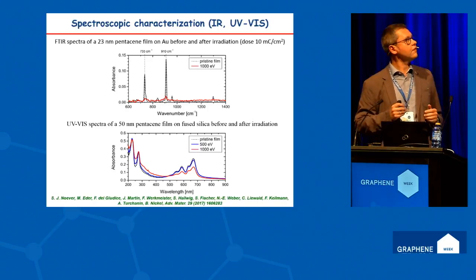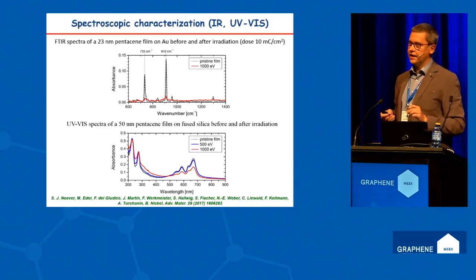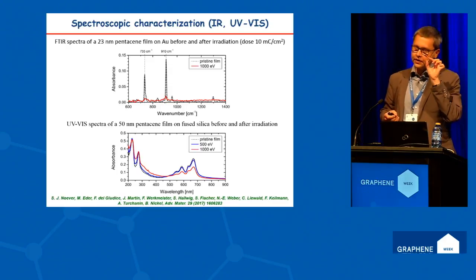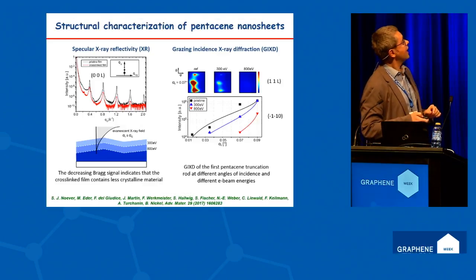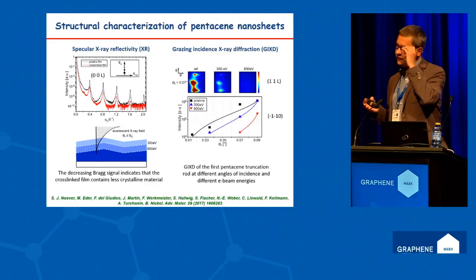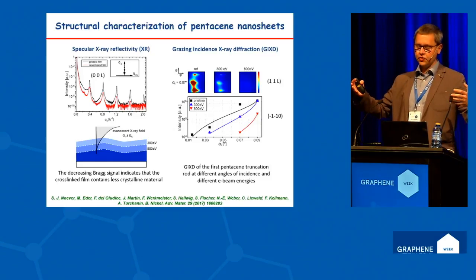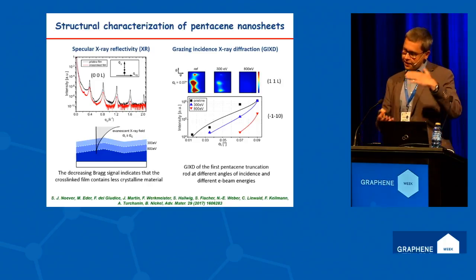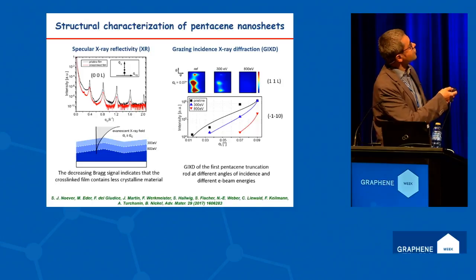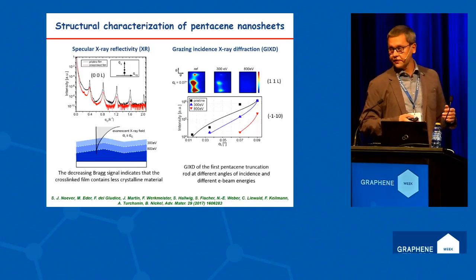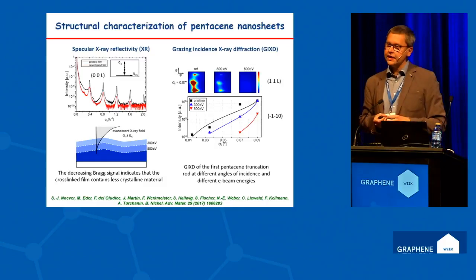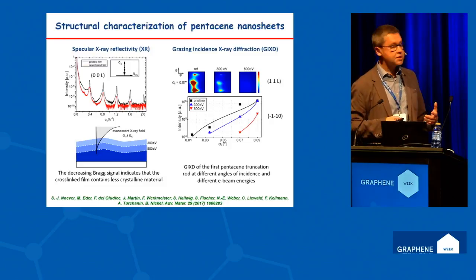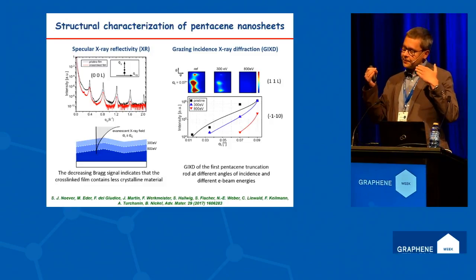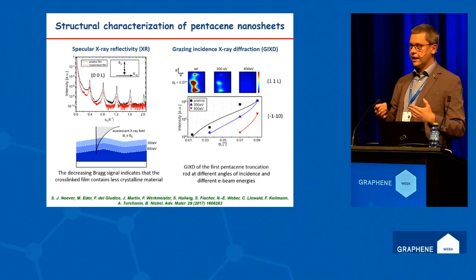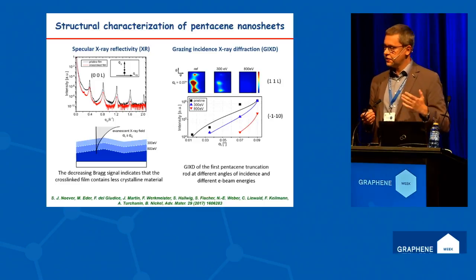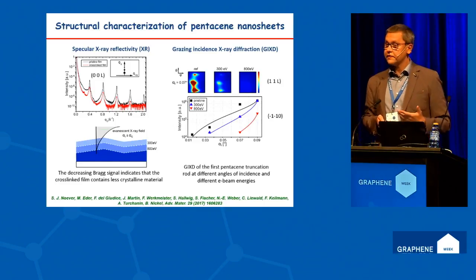This is a summary of spectroscopy data where you see, depending on the electron beam energy and dose, we can tune the thickness of this cross-linked layer very well. And finally, to convince even ourselves that the material still consists of the stabilizing top layer and a perfectly crystalline rest, in the group of Bert Nickel, very detailed measurements of X-ray specular reflectivity and grazing incidence X-ray diffraction have been conducted, which confirmed that in this way we can stabilize the film by introducing a cross-linked layer on top, which is only 3 nanometers thick, while preserving the perfect crystallinity of the remaining pentacene sheet.